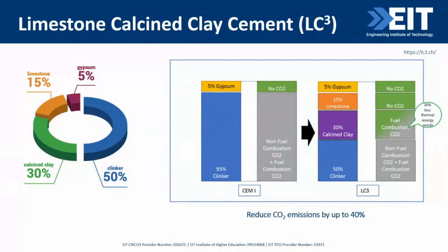Also, low energy is consumed in calcination at a lower temperature of clay. For clay, we need a temperature of about 750 to roughly 850 degrees Celsius. But for clinker, if you can still remember, the temperature is actually 1,450 degrees Celsius. So we only need a lower temperature for clay than that for clinker. As a result, LC3 can reduce carbon dioxide emission by up to 40%.